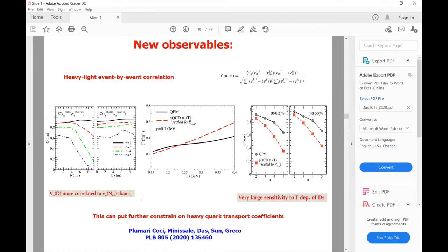In between, there are also some other new observables, and recently one of them is the event-by-event light quark, heavy quark correlation. That is the vn-vn correlation between light quarks and heavy quarks, and the linear correlation coefficients, which are really very sensitive to the heavy quark transport coefficient. As we can see, here is the transport coefficient, the drag coefficient, computed in two models. One is PQCD with running coupling, the other is a quasi-particle model. And this temperature dependence is reflected clearly in the linear correlation coefficients. So if this is observed in experiment in the future, certainly it will also help to constrain the heavy quark transport coefficient.